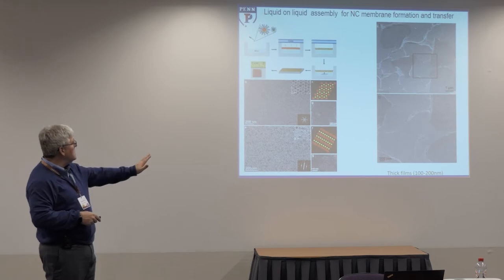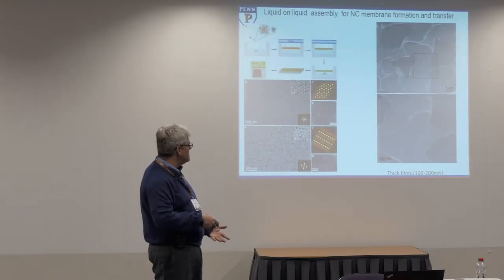And I want to be fair and just to better represent. So this is an ordered, oriented domain, but these materials are not single crystalline across their length. They're really polycrystalline materials. If you zoom out, you can see on a micron scale bar, or better, samples on 10 microns or so on. But the domains that we make in these systems are never more than, say, 100 microns in size. And so you have islands, sometimes with slight variations in thickness, but this represents the idea that you have a large oriented domain, a grain boundary, another domain. So you should think about these as being polycrystalline materials.